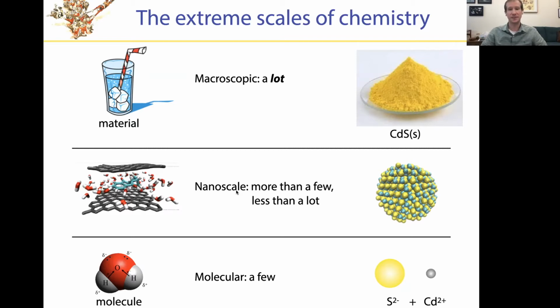More than a few in the sense that the conspiracy of many atoms and molecules has begun to produce emergent features that would be very difficult to anticipate from the individual constituents themselves. But less than a lot in the sense that the properties are really distinct in very interesting ways from their macroscopic counterparts. So these nanocrystals of cadmium sulfide have very interesting electronic properties. Water, when confined on a nanometer scale between sheets of graphene, can be a very different solvent for chemistry.